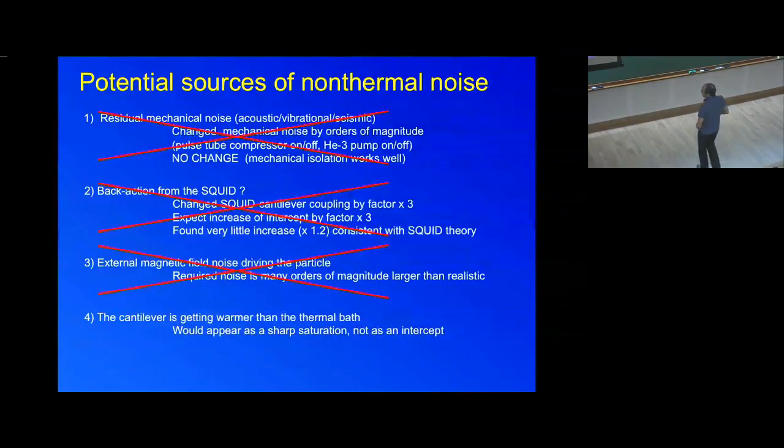Yeah, so I agree. The dissipation here is mostly due either to two-level systems or to surface dissipation. So if you have some dirt or some piece of anything, or even the oxide that forms naturally on the surface, when you have the bending, you can have some dissipation.